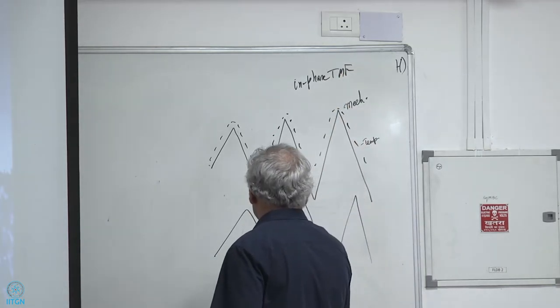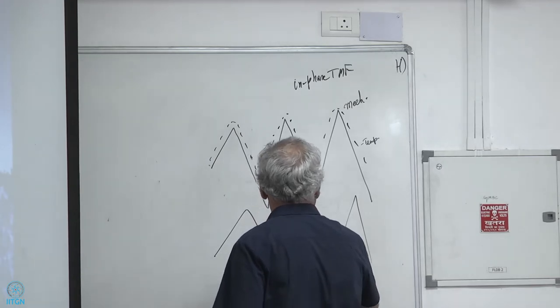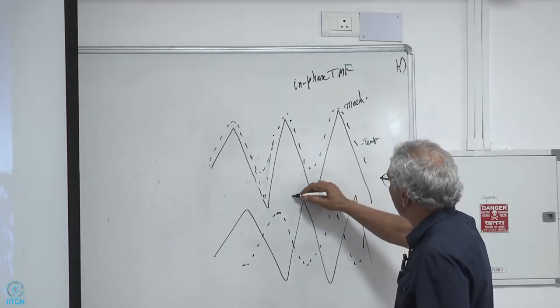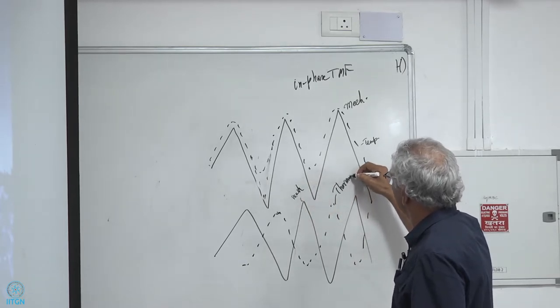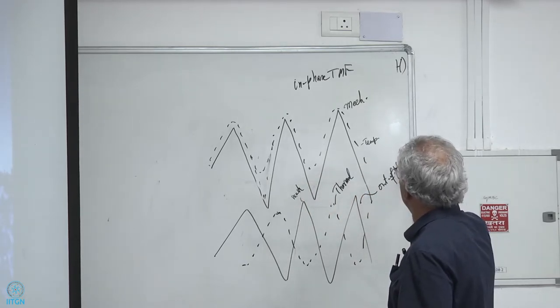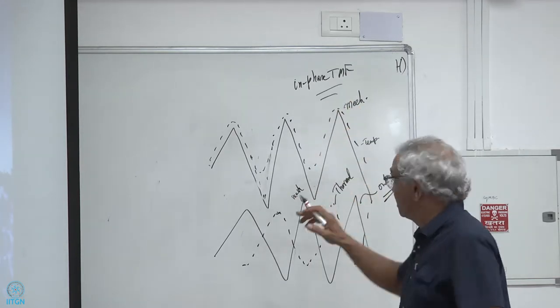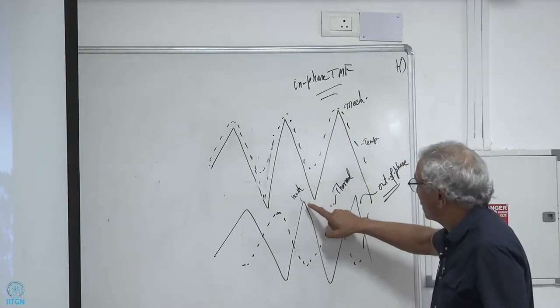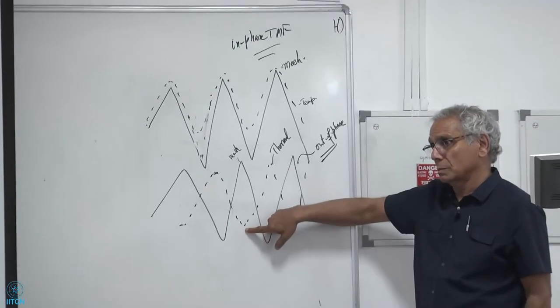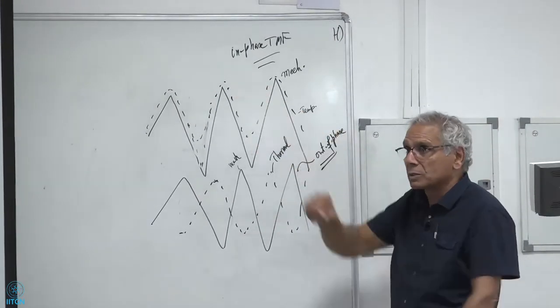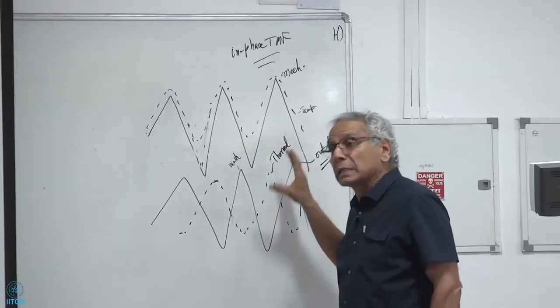And yes, go ahead. For welding, we pass in argon to prevent surface oxidation. So when we subject it to fatigue, can we prevent oxidation because we had passed argon? So you're talking about welding? Yes. During welding, you're pushing argon so that you push the oxygen out. So you get a better weld. Yes. Okay, you take that specimen which is welded, and now you're doing a test at very high temperatures. Can we prevent oxidation because already we had passed argon?